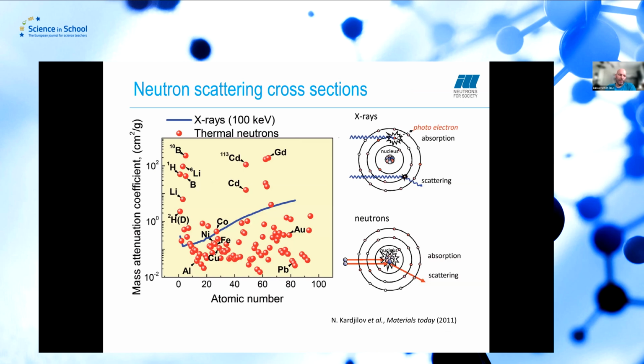So Alessandro has already shown the chemical table of elements with the gray values showing the relative absorption. So here I show the relative absorption, or the mass attenuation coefficient comparison between thermal neutrons and 100 keV X-rays. The X-rays, as Alessandro has already said, interact with the electron shell of the atom, while the neutrons interact with the nucleus. And what we see is a continuous Z dependence for the X-rays, but the neutron cross sections are very much scattered. So you can very well distinguish, in many instances, neighboring atoms with neighboring atomic number Z.